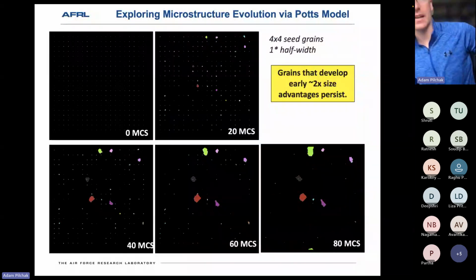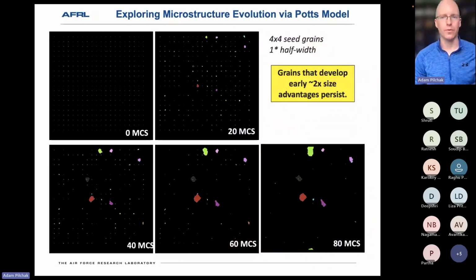So in this case, we're looking at 4x4 seed grains with a really strong 1 degree half width on the texture component in the background. At the initial condition, and then we see these 4x4 seed grains after 20 Monte Carlo steps. Some of them have disappeared. Others have started to grow and expand. At 40 Monte Carlo steps, we have more that have disappeared. Some which started to grow have increased in size.